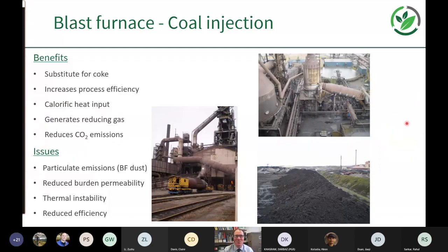The benefit of using this is it substitutes for a portion of the coke. Coke is produced by heating coal in an inert atmosphere, and it requires a lot of pre-processing. There's a lot of emissions associated with it. It's one of those things that you try to minimize, really. So coal injection improves this process efficiency, raises the heat, generates a reducing gas, and consequently, by improving the yield, it reduces CO2 emissions. But there are potential issues from it because of particulate emissions, which then hinder the gas permeability through that burden of raw materials, which I explained earlier in the countercurrent reactor.